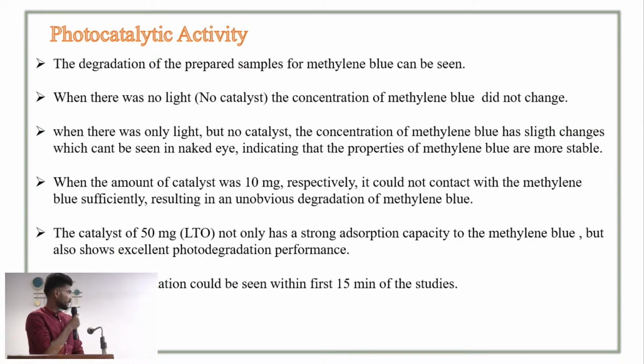Photocatalytic activity: the degradation of methylene blue by the prepared sample can be seen. When there is no light and no catalyst, the concentration of methylene blue did not change. When there is only light but no catalyst, the concentration of methylene blue has slight changes, which cannot be seen with the naked eye, indicating the properties of methylene blue are more stable. When the amount of catalyst was 10 mg, it could not contact the methylene blue sufficiently, resulting in unobvious degradation of methylene blue.